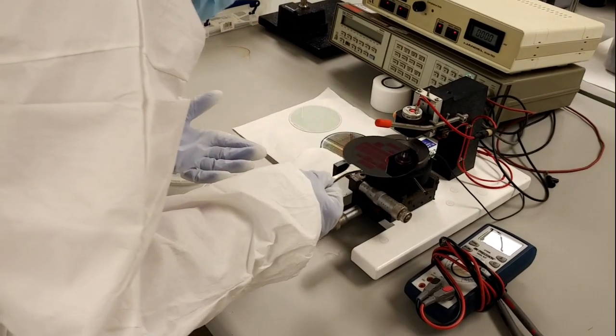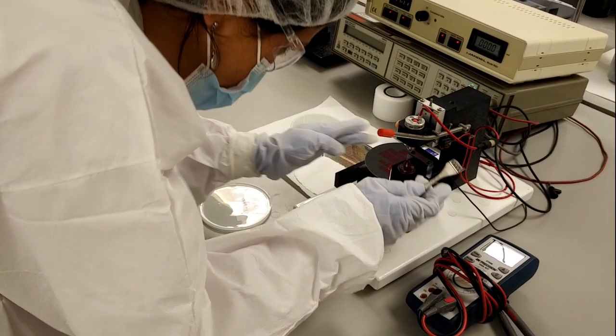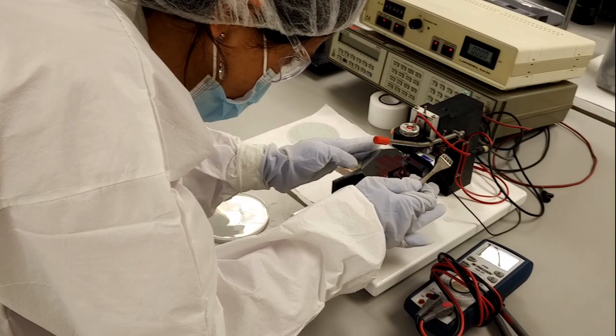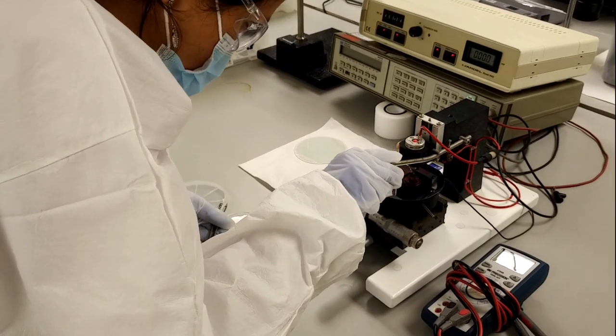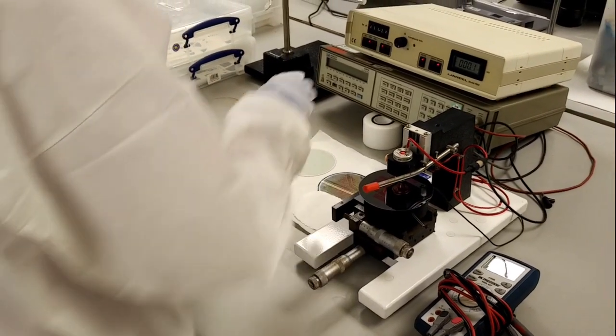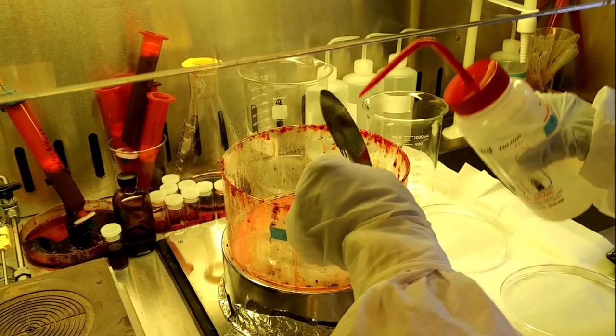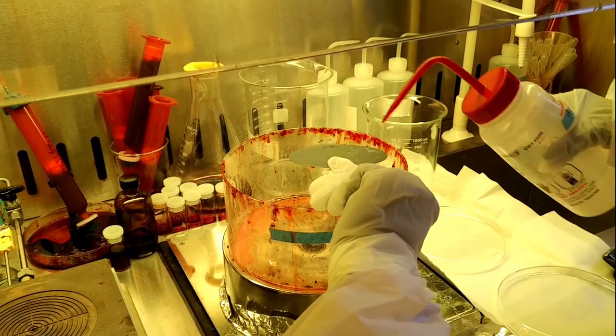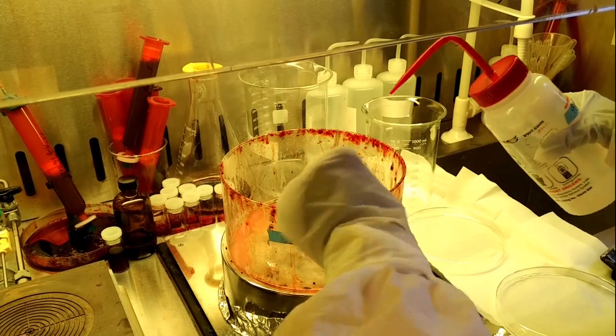If there is an oxide layer on the wafer, the resistance seen by the meter is infinite. Resistance in the kilo-ohm range indicates the oxide layer has been removed and the silicon is bare. Finally, the wafer is washed with acetone to rinse off the remaining photoresist, and it is now ready for doping.